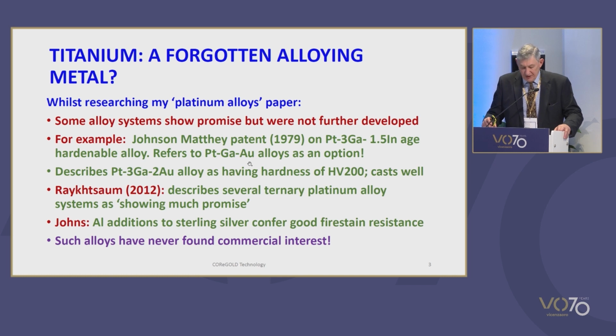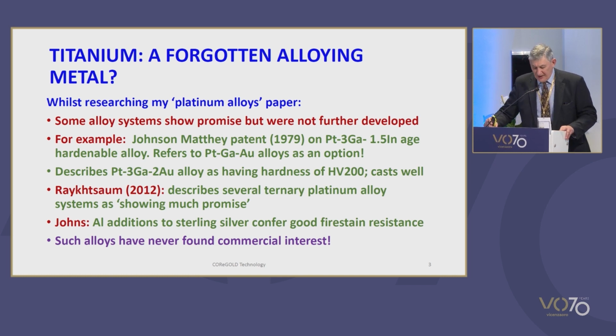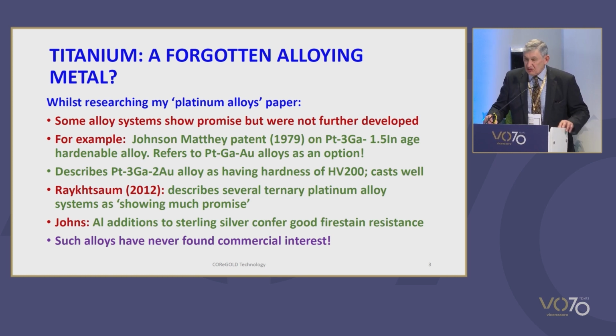It was while researching my recent review of platinum jewellery alloys that I became aware of alloy systems that had showed much promise, but were never further developed to commercial application for jewellery. An example of this is described in a Johnson Matthey patent for the age-hardenable platinum gallium indium alloy, platinum 3 gallium 1.5 indium. In this patent, the inventors also refer to platinum gallium gold alloys as an option, with the use of yttrium additions of about 0.1% as a deoxidizer. The platinum 3 gallium 2 gold alloy is claimed to have a high hardness of 200 Vickers. Such gold alloys are said to cast well.